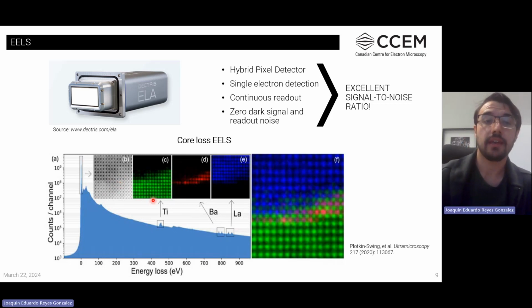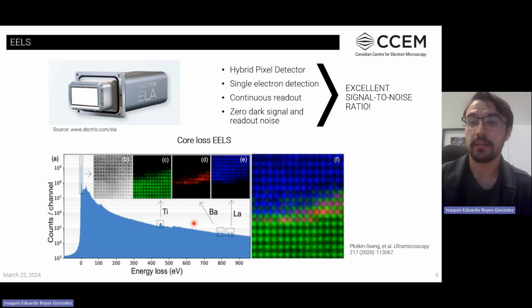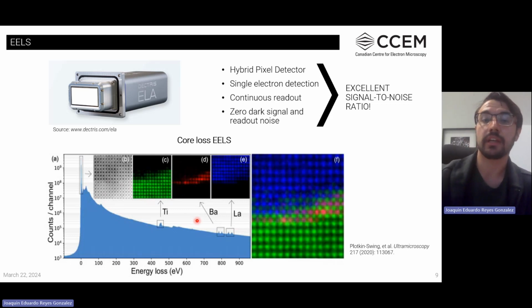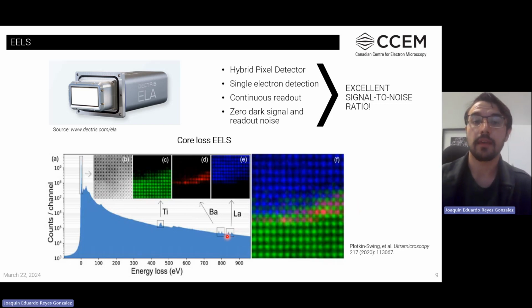And then we have the resulting positions of the titanium, barium, and lanthanum atoms extracted by the background subtracted data of their ionization edges. And finally, we can observe the really high quality RGB picture where we can identify the atomic positions of all the elements that we extracted, very clearly defined and easy to interpret, and then to associate with further other properties.